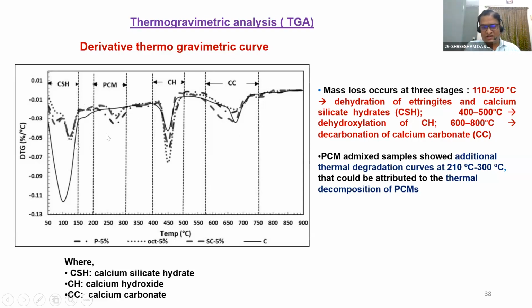So what we realized is that this peak is getting smaller, meaning the hydration in the initial days is slowed down, and it is pronounced in one additional temperature range. And that is nothing but the thermal degradation curve for the PCMs, between 210 and 300 degrees centigrade.